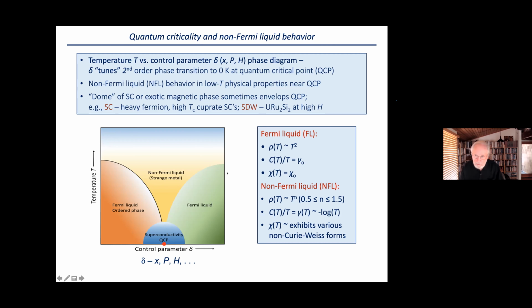And so in the Fermi liquid, you get these usual Fermi liquid properties at low temperatures in the resistivity, specific heat, and susceptibility, temperature dependencies, I should say. And then for non-Fermi liquids, you find that the resistivity can have exponents ranging from 0.5 to 1.5, roughly speaking, but usually they're close to 1. And then C over T usually diverges logarithmically. And susceptibility is a little bit more difficult to interpret, but one finds various non-Curie-Weiss forms.